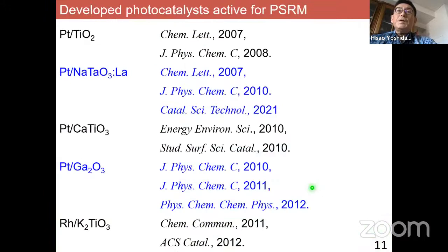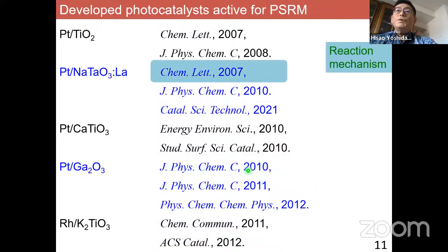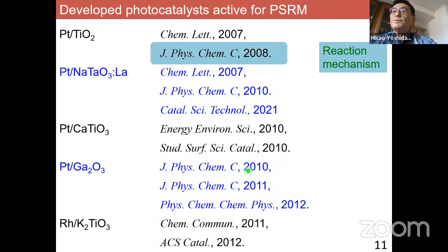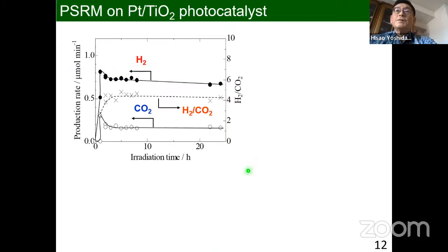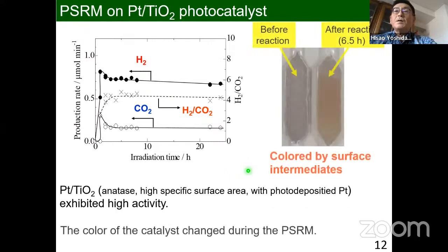And after that, we developed some catalysts in this way. Today, I want to deliver the story of the reaction mechanism study. Here, the same graph by using the titanium oxide with platinum co-catalyst. In this case, it's active. However, we found an interesting phenomenon on the surface of the catalyst. Something accumulated. The color is brown. So we wanted to know what this is.